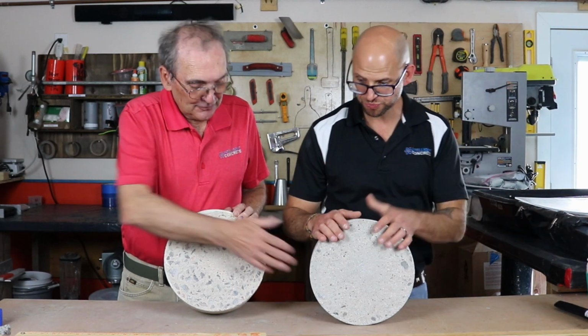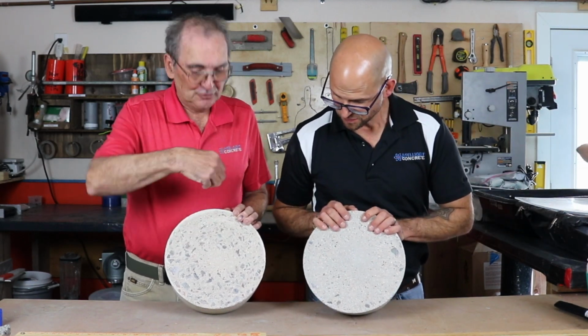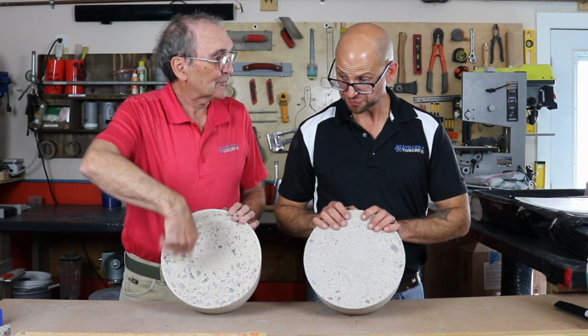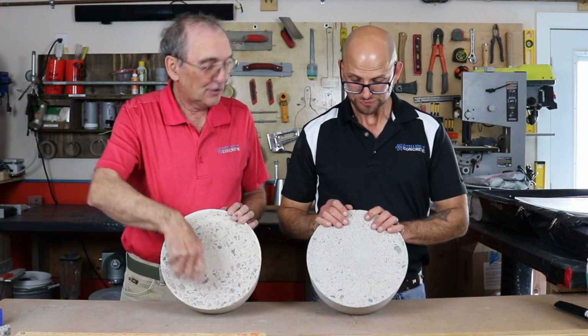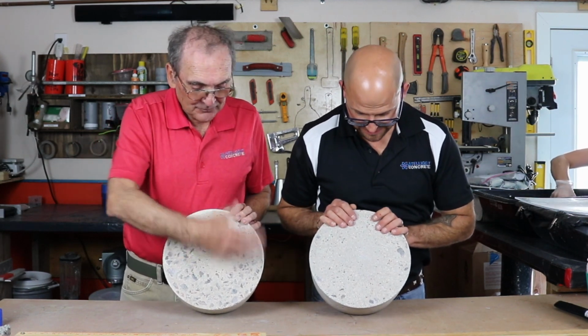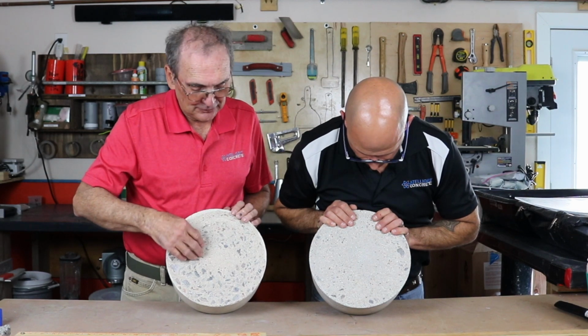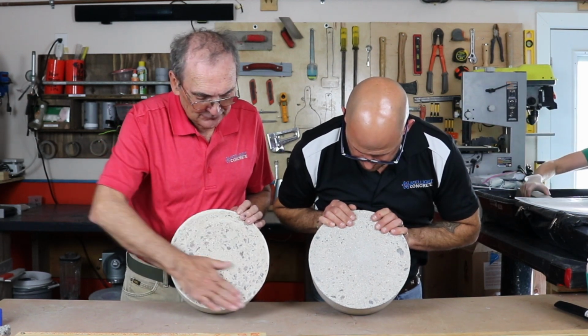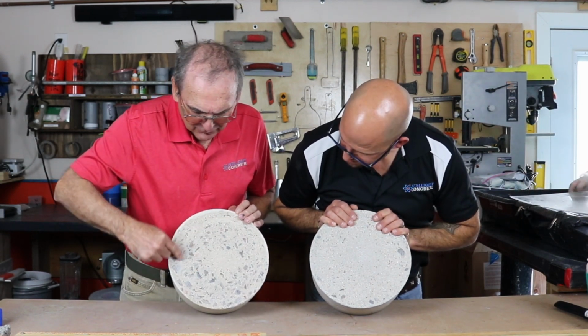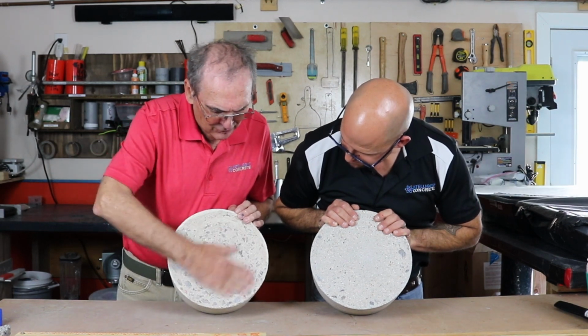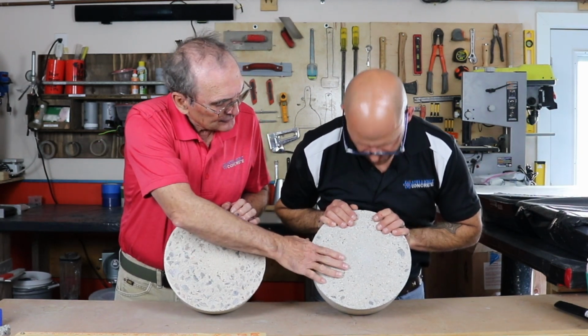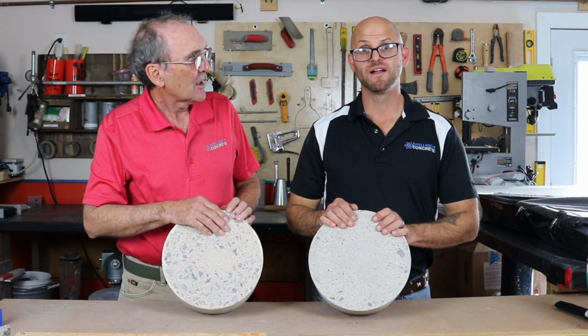So here we've got two samples we did underwater. We switched the balls around, the gradated steel balls with a paint mixer. And it's just like a field situation, a miniaturized field situation. Here's the reference. Look at all this gravel. Look at this groove we made. Look at all this abrasion. Here's colloidal silica. What's that look like, John?